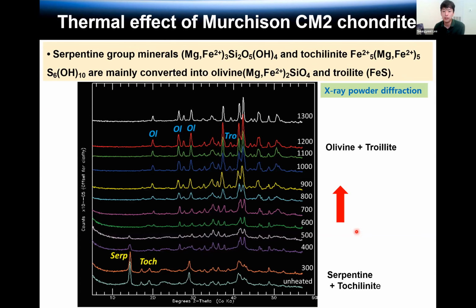Also, this heating sample also matches with other tools. So this is X-ray powder diffraction data at each temperature, from initial up to 1300 Celsius degrees. So we can see initially serpentine and tochilinite are dominant. During the heating, these phases become olivine, and troilite is a dominant phase.